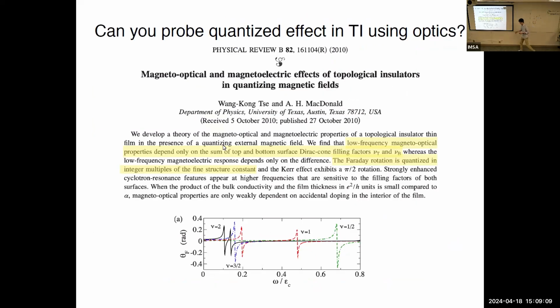Okay, and so the next question is, what are the ways to measure this magnetoelectric effect in a real experiment? And one of the ways to do it, as is highlighted in this paper, is to measure how the polarization of light changes while it passes through this slab of topological insulator. And it was shown, theoretically shown, that the Faraday rotations are going to be quantized in terms of the fine structure constant alpha. And they're also going to be proportional to a sum of the filling factors on the top and bottom surfaces of the TI.